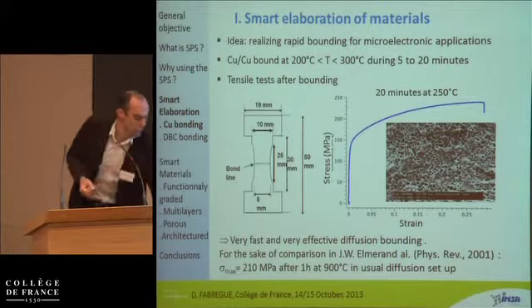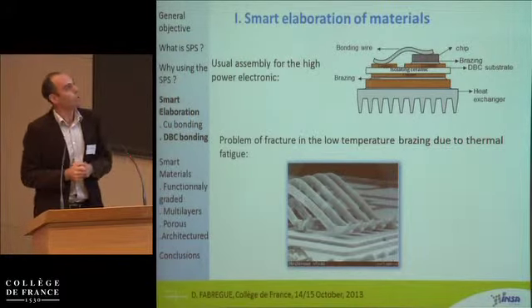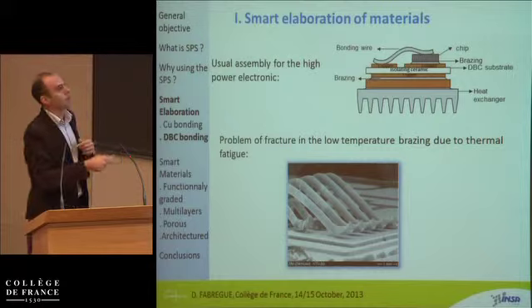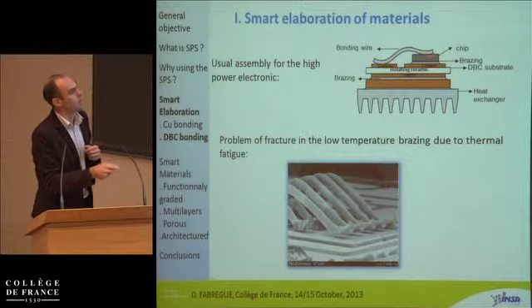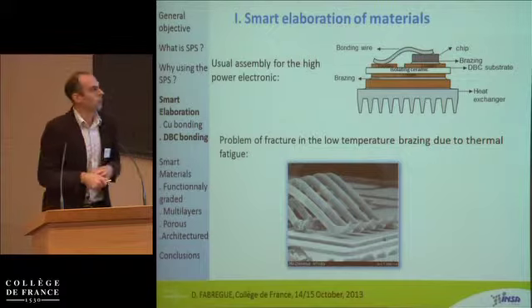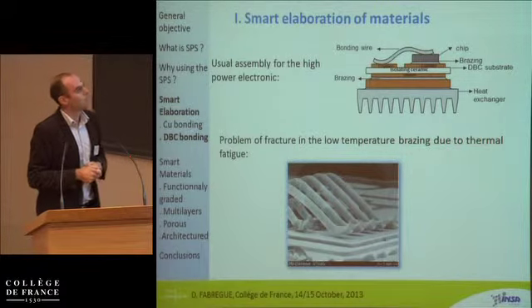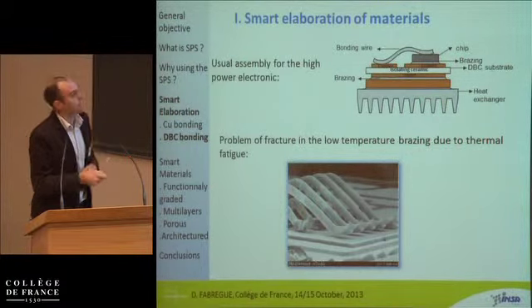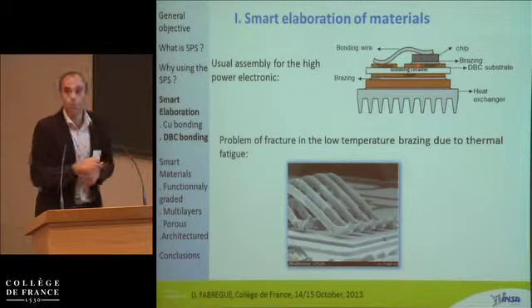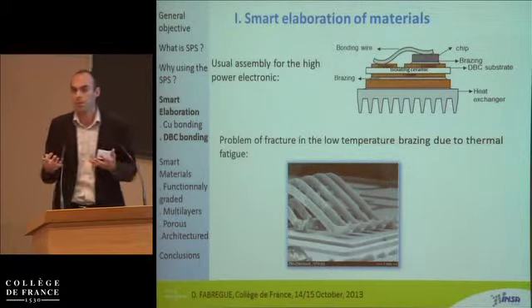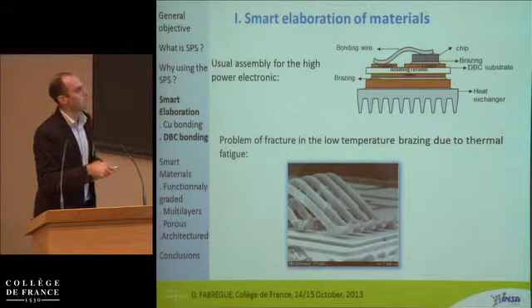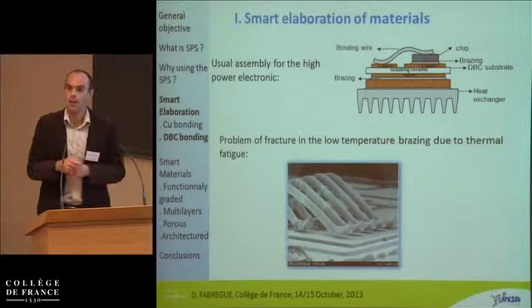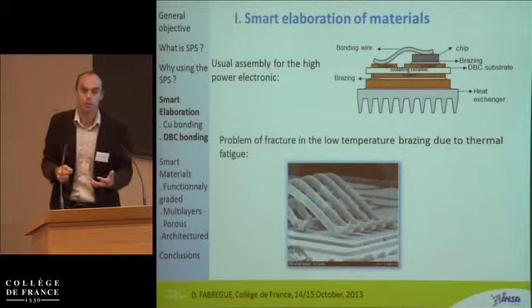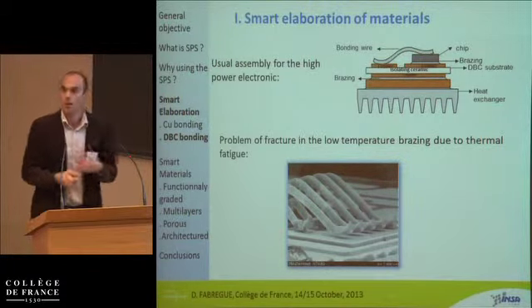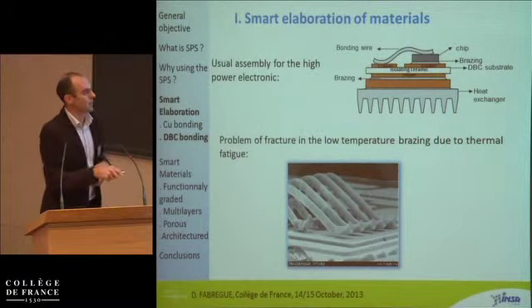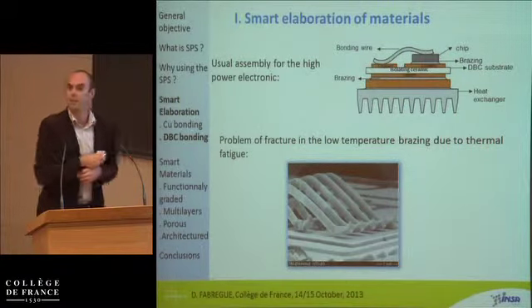So why do we choose that system? Because if you look now at power electronics, you have this kind of complex structure where you have a chip and then you have some insulator and copper parts. And there's a big problem: for example, when you want to put a chip on copper, for example to dissipate the heat of the chip or to put connections, then you have to braze it. And as you braze it, you introduce new materials, and when it's submitted to thermal fatigue, it can break. And as you can see, the connections here are not connected anymore.